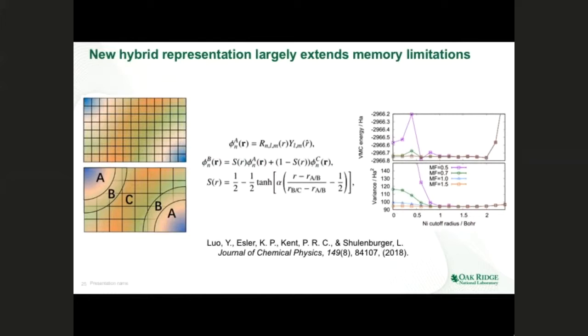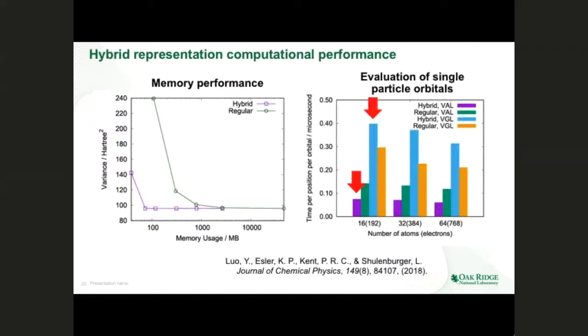this work was performed on nickel oxide, and using a suitable cutoff radius, we can reduce the wave function density by half. That would correspond to very large memory gains. You can see that the memory gain from using this scheme, on a log scale, is more than a 10 times reduction in memory.